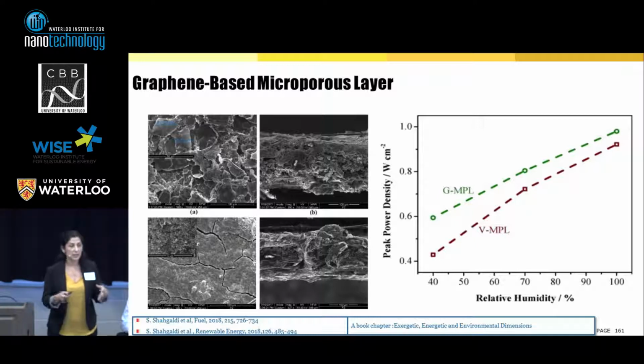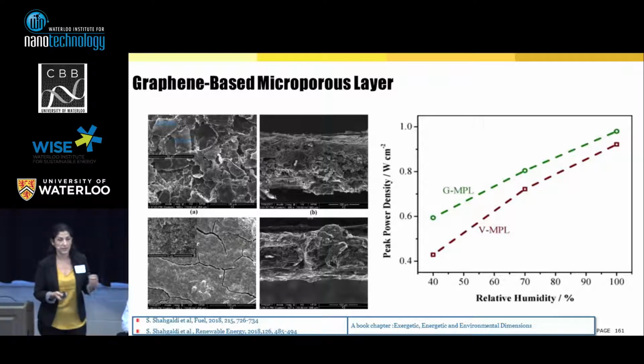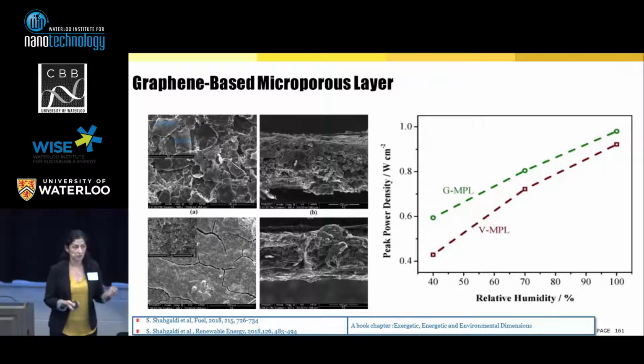So we did a lot of research on new materials like graphene, Vulcan, and high surface area carbon. We made a lot of microporous layers for our fuel cell. And we found out the graphene with the optimized thickness and electrical conductivity shows a very good result as a microporous layer, and it increased the durability, and it's really resistant to corrosion, carbon corrosion.